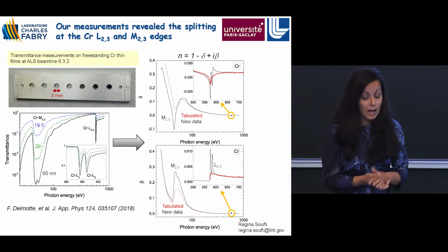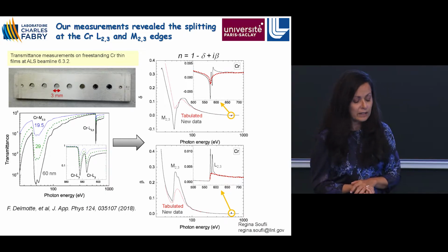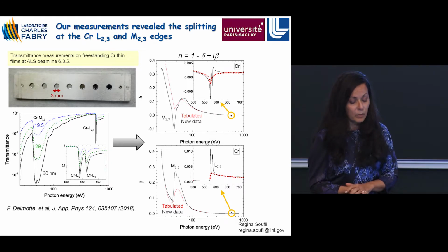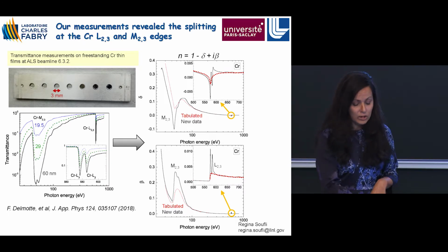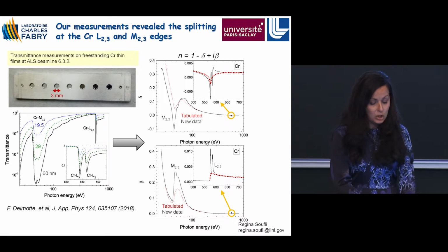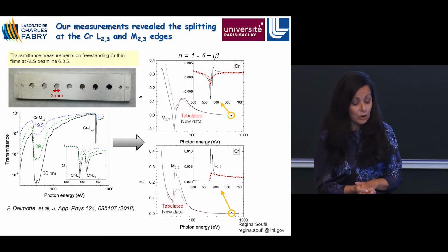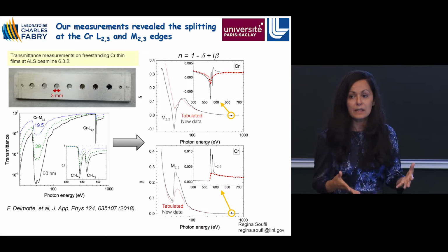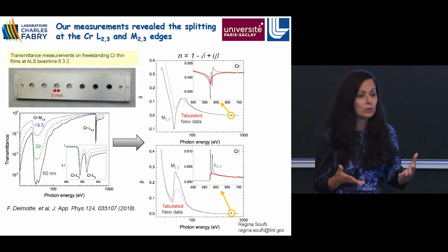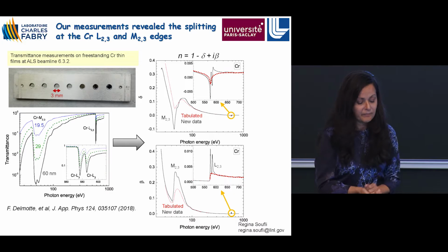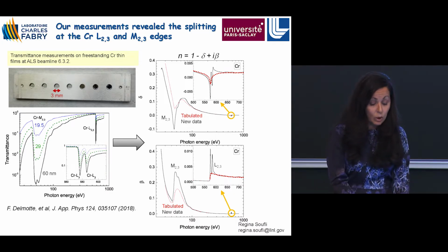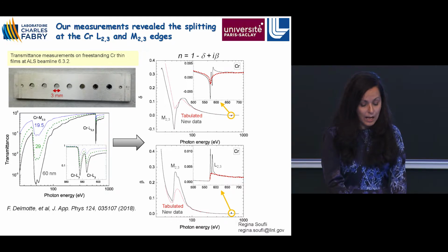So we decided to do these very important measurements for the refractive index of chromium, since it is a very important material for multilayers. This work was led by Frank Delmotte. I'm showing here first the thin freestanding chromium films that were up to 20 nanometers in thickness and thicker. They were prepared and mounted by our colleagues at Lawrence Berkeley Laboratory, and you can imagine that these films have to survive the pump down in vacuum and venting that are thinner than, they're just a few atomic monolayers thick, basically. And so first we had to do that.